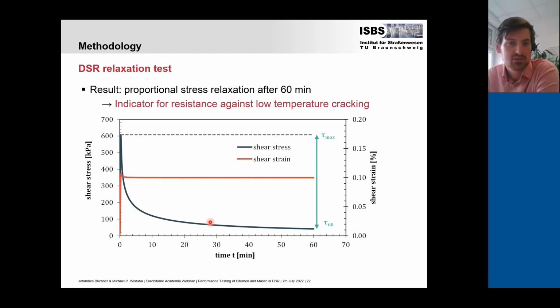So here you just see the result of this relaxation test, where we applied a constant shear strain of 0.1% for 60 minutes. We measure the shear stress, which reaches a maximum value in the beginning of the test, and then constantly decreases due to relaxation within the material. And we finally use the proportional stress relaxation, so the proportion of the stress which is relaxed from the maximum stress, as an indicator for resistance against low temperature cracking.